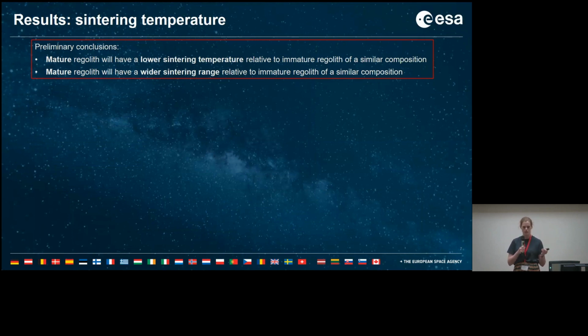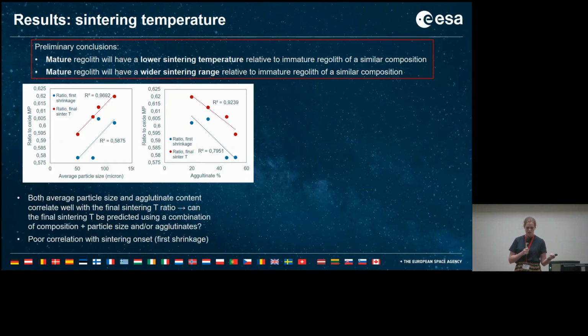So looking at those conclusions that relate to the maturity of the sample, we can compare it to what maturity really means. So here we can compare the ratio observed to the average particle size and the agglutinate content. And we see that both of these correlate really well with the final sintering temperature that was observed. It's not surprising that they both correlate because they also correlate to each other. So trying to tease out the difference between particle size and agglutinates is one of the next steps in the project. So this maybe suggests that the final sintering temperature of a given material might be able to be predicted based on a combination of the composition and the particle size or agglutinate.